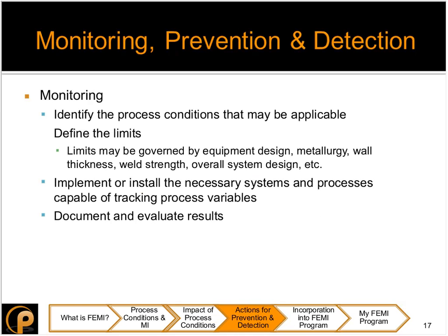Now, let's look at some ways that you can monitor, prevent, and detect some of these damage mechanisms that may be present. The first thing would be to monitor your equipment. The first thing to do is identify process conditions that may be causing these damages to your equipment. The next step is to define limits that may be governed by the design of your equipment, your metallurgy, your wall thickness. A good example is your maximum allowable working pressure, or your MAWP, which may be defined by your material strength, which is a characteristic of your metallurgy, your wall thickness, and your weld strength, and can affect what operating limits you might have on your equipment as far as pressure is concerned.